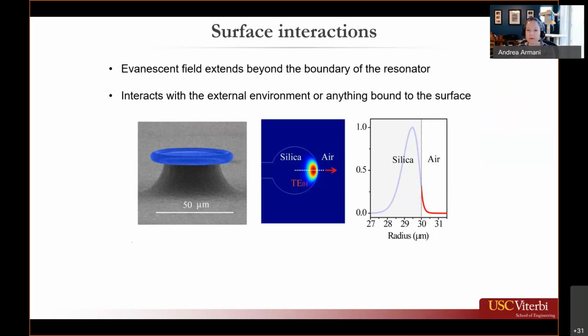So this series of pictures, the first one shows a colored SEM image of a whispering gallery mode resonator. The second is a cross-section of a finite element method model of just that toroid part, showing the location of the circulating optical field, identifying where the silica toroid is, as well as where that silica-air boundary is located. And then the white dashed line is a cross-section through the highest intensity region of that optical field. And then the cross-section is plotted in the graph on the far right, highlighting where the silica-air boundary is. So as you can see in the graph, while the majority of the field is located in the silica, that little red tail is what's at the silica-air interface and located entirely in the air.